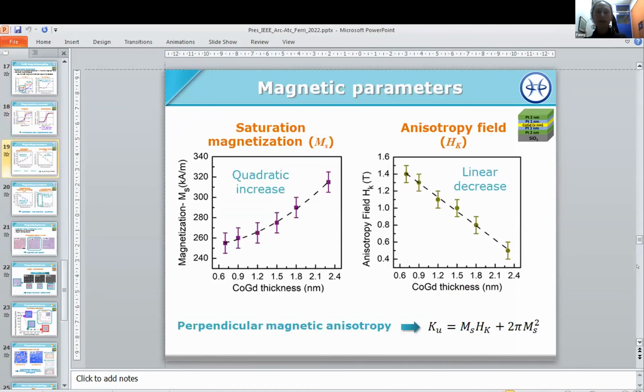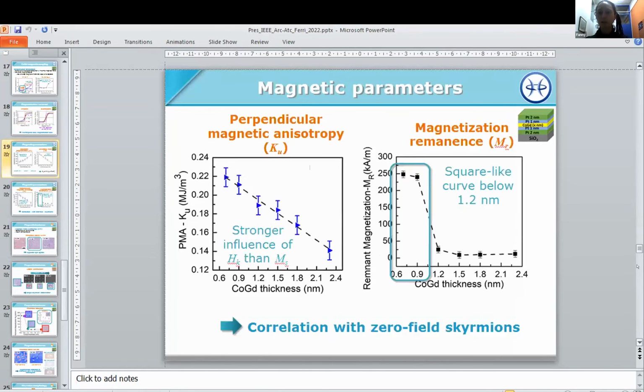From this curve, we extract the saturation magnetization and the anisotropy field, to be able to calculate the perpendicular magnetic anisotropy. Something important to point out: if you look at the saturation magnetization as a function of the thickness, we have a quadratic increase, while for the anisotropy field we have a linear decrease of this field when we increase the thickness. And so calculating the magnetic anisotropy, we see that we have a linear decrease. So in this system, we have a stronger influence of the anisotropy field than of the saturation magnetization.